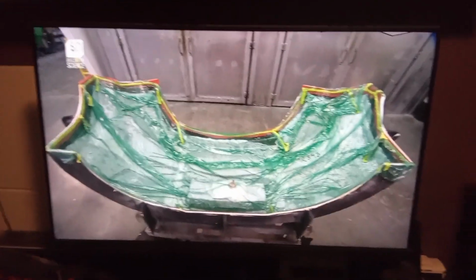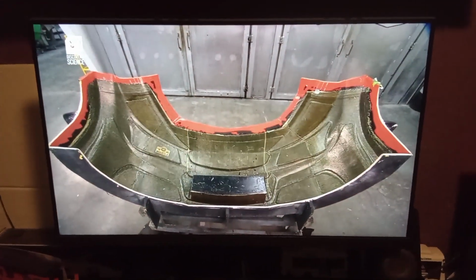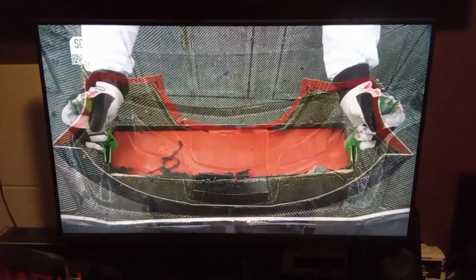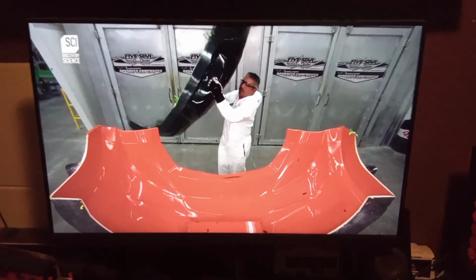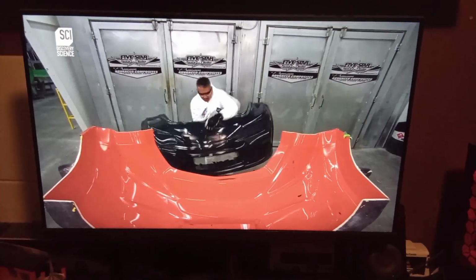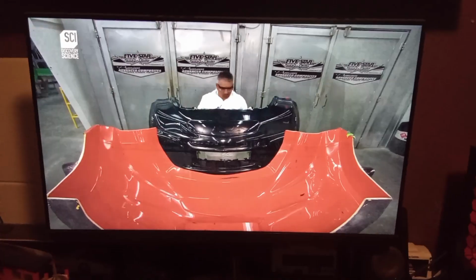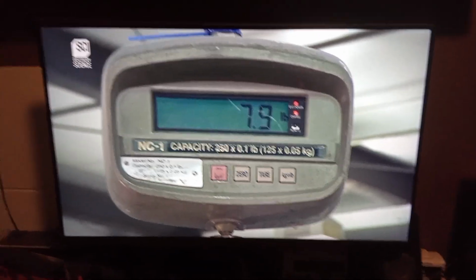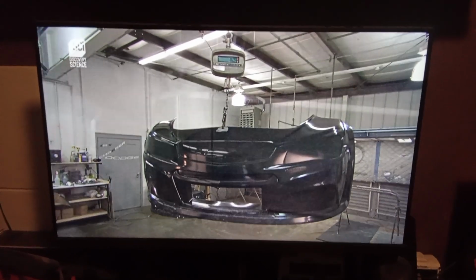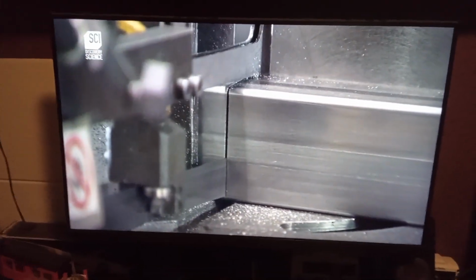It's then into a hot oven to bake for 3 hours. This activates the epoxy and the layers of carbon fibre and Kevlar fabric become one. The completed stock car panel is then removed and inspected. It's then taken to a weigh station. At just under 3.6 kilograms, the part is lightweight yet virtually shatterproof.